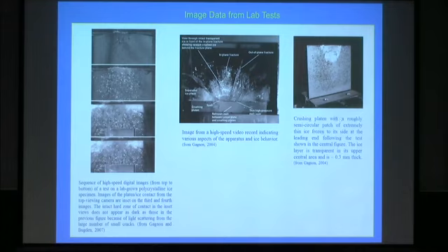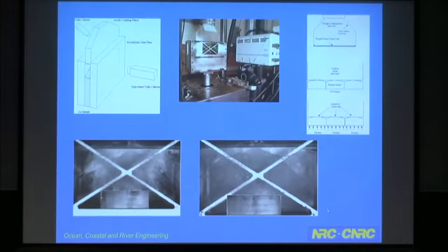Actually, that's some of the slurry layer left on the platen after the test, so that's kind of frozen onto the platen. We also did bigger tests, same idea. In that case, we had a bigger indentor, bigger ice, 3 pressure sensing strips instead of 1. And same sort of thing, the ice has some fractures in it, but the hard zone is here, and the crushed material is at the side, so the pressure reading shows that the hard zone is there.